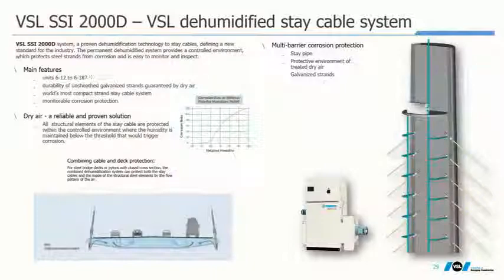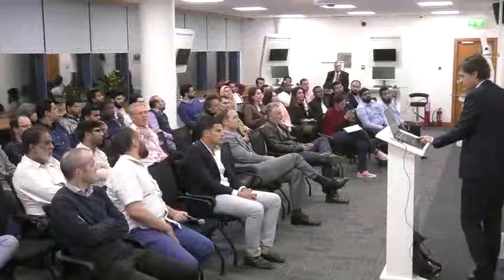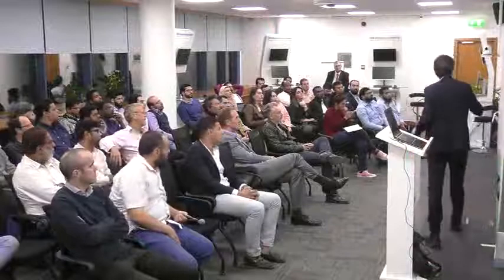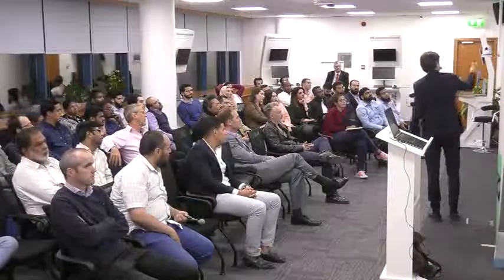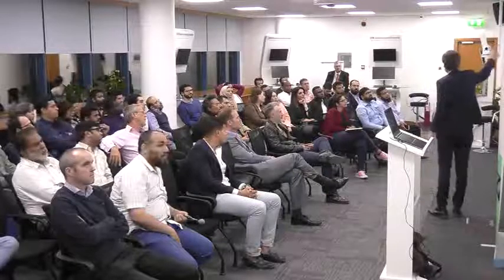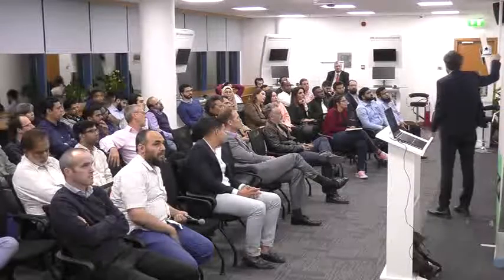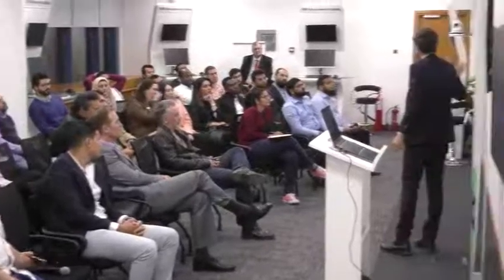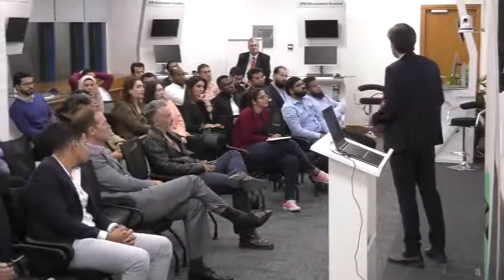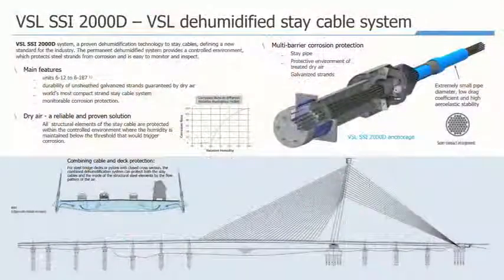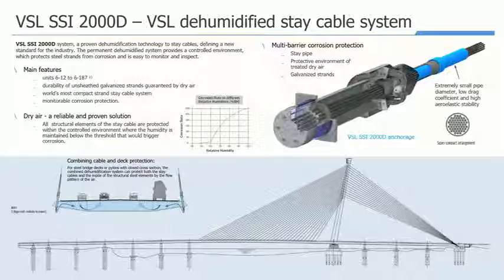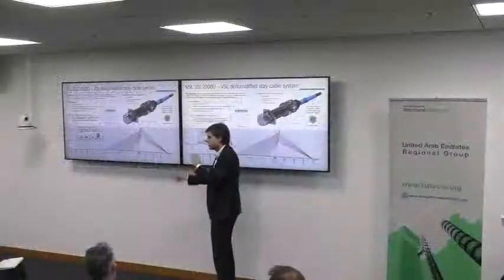So is it a continuous process, dehumidification, or is it done at some intervals periodically? If you see that graphic here, these are the corrosion rates according to humidity. And what you find is that with a relative humidity of 60% and below, you have almost no corrosion. It picks up very fast afterwards, but below 60%, no corrosion happens. And all dehumidification plants usually work at 40%. So the idea is to have a closed loop of dehumidification. This is the principle applied in this Hong Kong project. You keep recirculating the same air, and your machine is just there to compensate for leakage. As soon as you have leakage, you have to refeed with dry air, so you dry only the piece of air you add on top in the circuit.